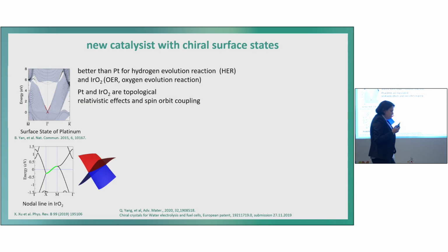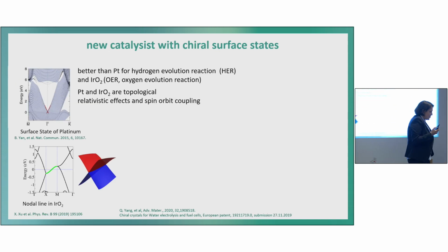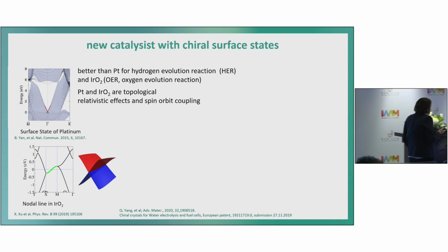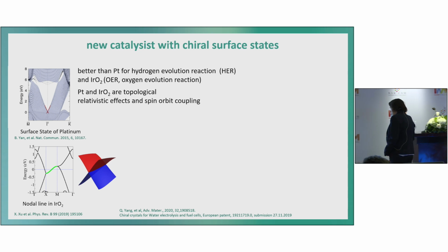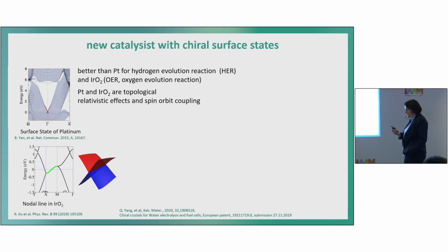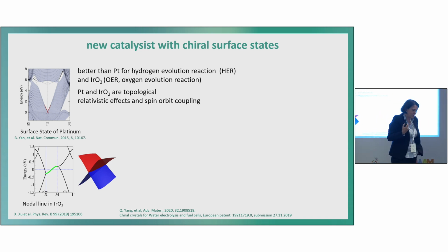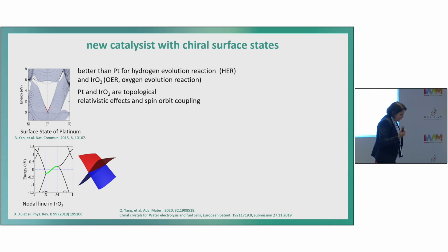Okay, so we thought already with the Weyl semimetals we are interested to do catalysis, and we did catalysis on the Weyl semimetals, even in the magnetic field, because if you see a magnetoresistance effect, you should be able to influence the catalytic properties in the magnetic field, and we did, and we saw it.